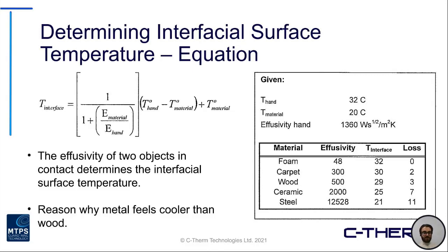This is really, call it, the math behind why, per se, a metal would feel cooler to the touch than wood, as you can see based on the effusivity differences. In the example here on the right, you can see that if you run this calculation, your steel would result in essentially an interfacial temperature difference of around 11 degrees, whereas something much lower in effusivity, such as a carpet or a wood, is much less. Therefore, it's pulling less thermal energy away from your hand, and therefore not feeling as cool to the touch. So there's actually a way to not only quantify the touch performance using effusivity, but also try to understand how that overall temperature difference will be experienced in the actual end use condition here.